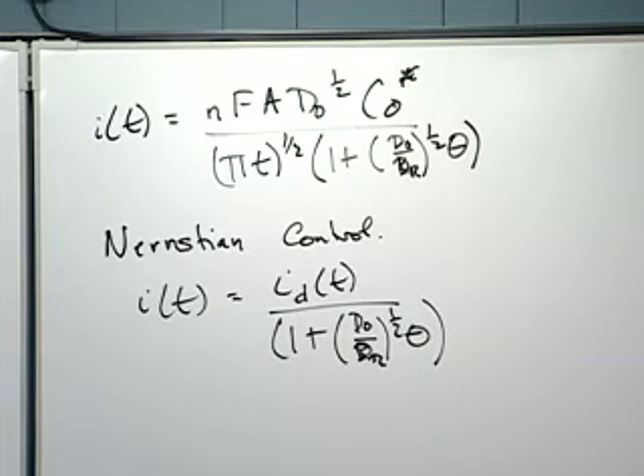On the negative side, don't forget about this, that at time equals 0, this equation is undefined, so we can't use the very early time. In addition to that, if we have a large RC time constant for our system, large compared to the time constant for this process, that is compared to the square root of the diffusion coefficient, if you will, we are not going to be able to see the Faradaic process under the non-Faradaic process.